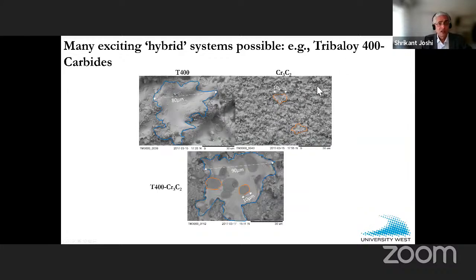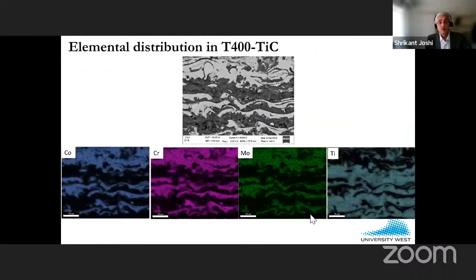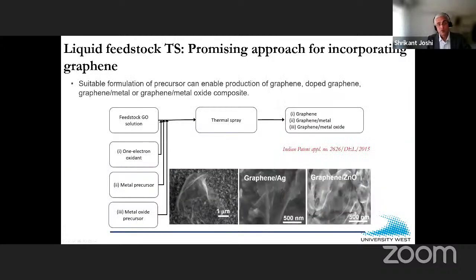One is incorporating carbides in, let's say, a matrix of Tribaloy. No good reason to use Tribaloy actually, except for the fact that we wanted to try this out and we had a Tribaloy 400 bottle sitting on the shelf there. But what this does is clearly show you this multi-component splatting in situ, and then the ability, of course, to control the carbide content at will and get good properties, right?